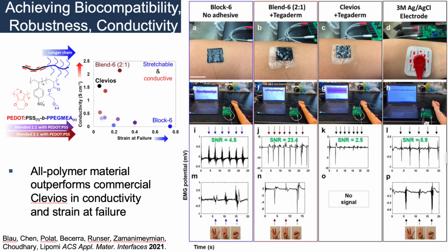When we applied these materials to the skin, this is a surface electromyography setup. We just have the fingers make some kind of nondescript gestures here, and we got the best signal-to-noise ratio using our material. And we shouldn't be too surprised because we have the best combination here of conductivity, but also a pretty good strain at failure. It's actually the most conductive material, but it's stretchable at about the level commensurate with what's needed for the skin.